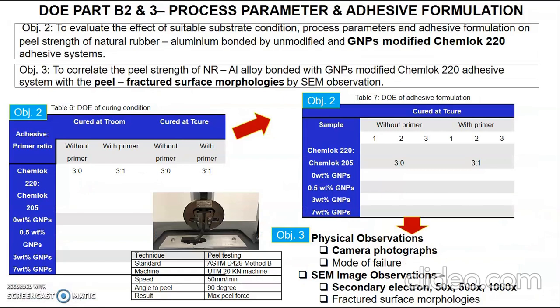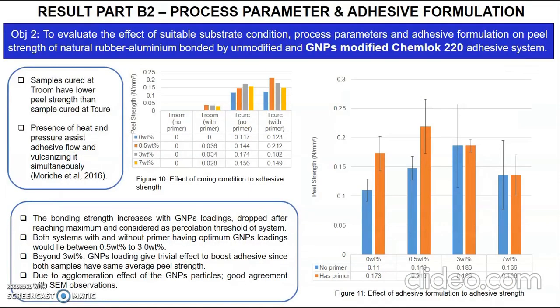The DOE for part B2 is the same as B1, which evaluates the peel strength value from the peel test, but the samples in B2 use the modified Chemlok adhesive system. Result part B2 is to achieve objective 2, the effect of curing condition on adhesive strength. You can see that T-cure is better than T-room due to the presence of heat and pressure that assist the adhesive flow. And figure 11 shows the effect of adhesive formulation on adhesive strength.